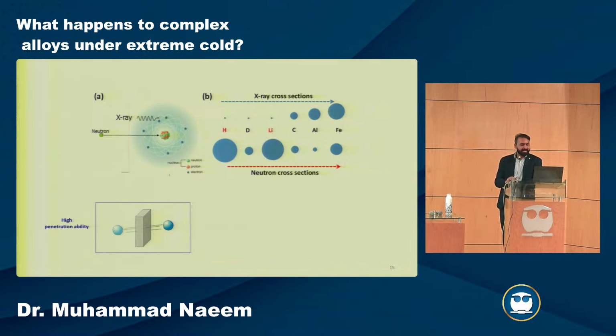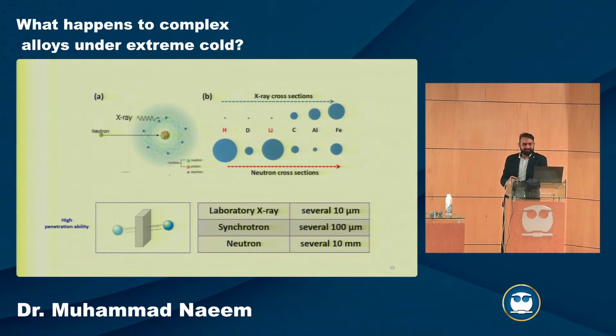I already mentioned that because of their large mass, as well as because they interact with the nucleus, they have high penetration. When we do lab XRD, the penetration is around tens of microns, so basically we're looking at the surface of the material, and you have to prepare your sample carefully. Synchrotron is also X-ray, but it is high energy X-ray diffraction, and you can go to much higher penetration, hundreds of microns, so one order of magnitude higher than lab XRD. With neutrons, depending on which kind of material you are looking at, you can go up to tens of millimeters. So you have to select your material and know whether it would be good or not.